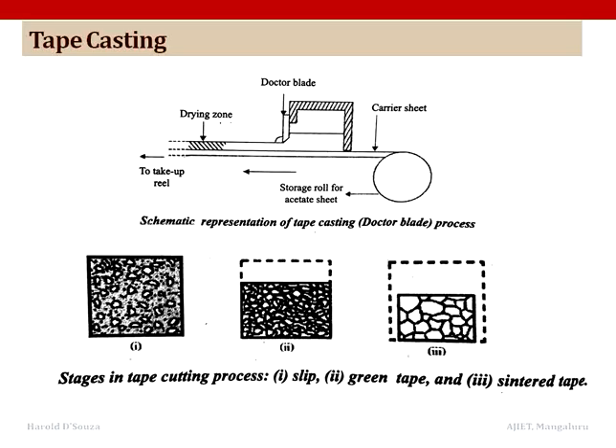The slurry is then fed onto a moving carrier film from the bottom of the reservoir. Now a powder slurry layer is deposited on a carrier film by the shearing action of the doctor blade. It is important that the slurry be free from air bubbles as they may lead to porosity in the strips, affecting the properties. Now during sintering the binder is burnt off first, and as the temperature increases densification of the material occurs. Present day units use an endless steel belt instead of a carrier tape. Now this process can be used to produce very thin tapes between 50 to 1000 micrometer thick. This method is widely used for producing electronic substrates, dielectrics for capacitors, and piezoelectrics for actuators.